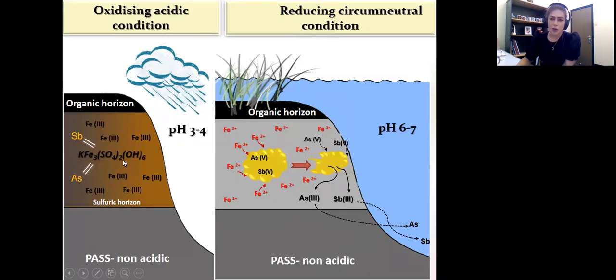oxidizing conditions, jarosite, for example, is one of the very common iron 3 containing minerals under oxidizing acidic conditions. And because this mineral has a really high surface area, it is generally considered a very potent scavenger for a wide range of trace metals and metalloids, including arsenic and antimony, which are my metalloids of interest. And I wanted to see if we have jarosite in our soil profile or in conditions relevant to acid sulfate soils, which could be similar for acid mine drainage affected environments too.